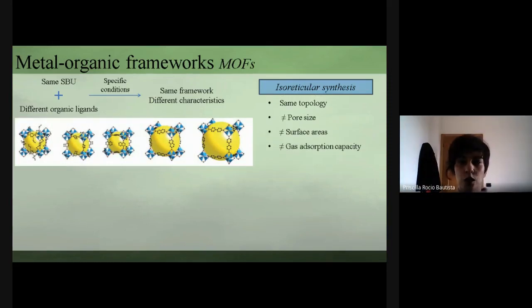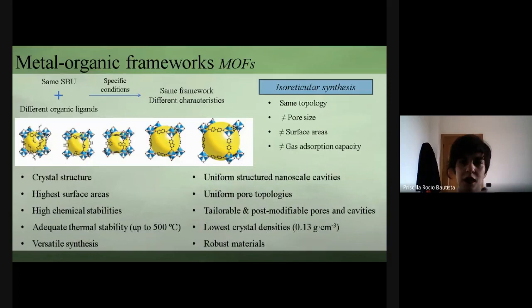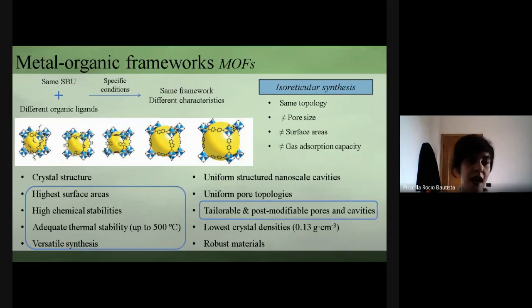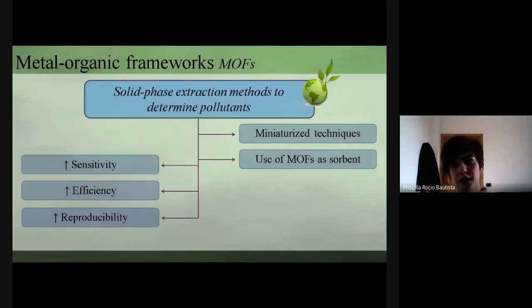In this slide is shown an example using the same secondary building unit and different organic linkers. The final MOF presents different pore size, different surface area, and different gas adsorption capacity, but maintaining the same topology. MOFs present a variety of interesting properties, and among them could be highlighted that they have the highest surface areas known, they have an excellent chemical and thermal stability, their synthesis is versatile, and their pores and cavities are tunable and can be modified post-synthesis.